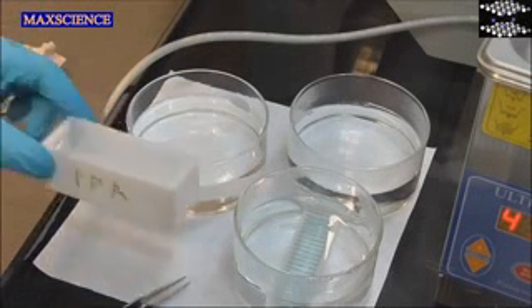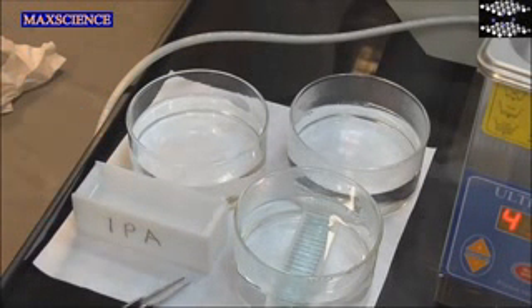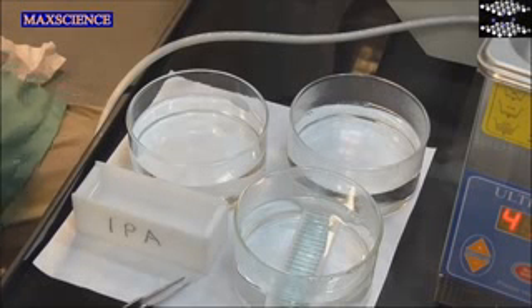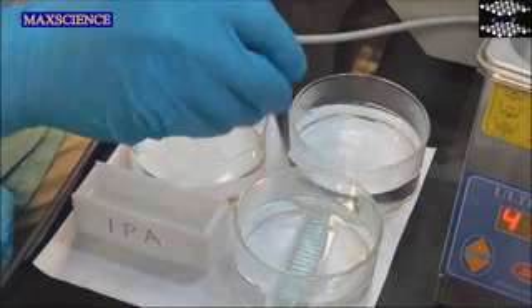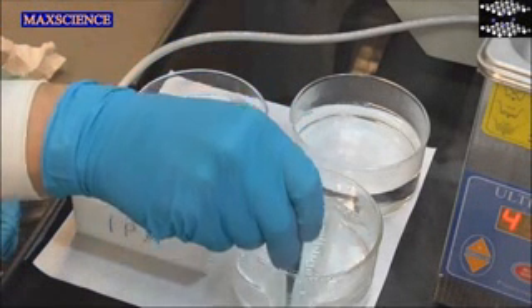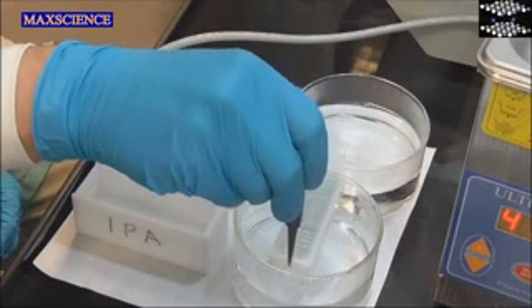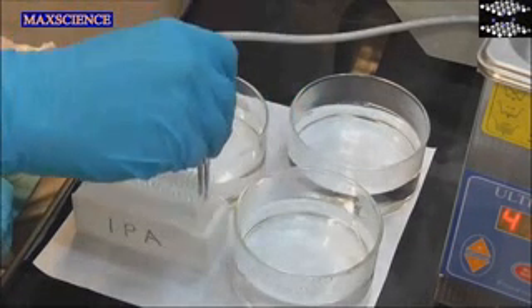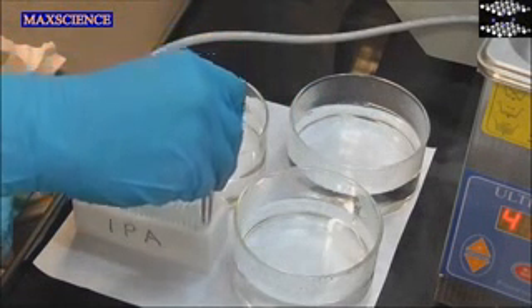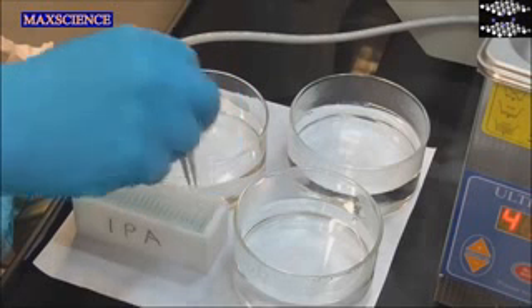The substrates should then be cleaned in isopropyl alcohol. Replace the substrates in a polypropylene beaker having a tight-fitting lid. This lid prevents the IPA from evaporating during the sonication.